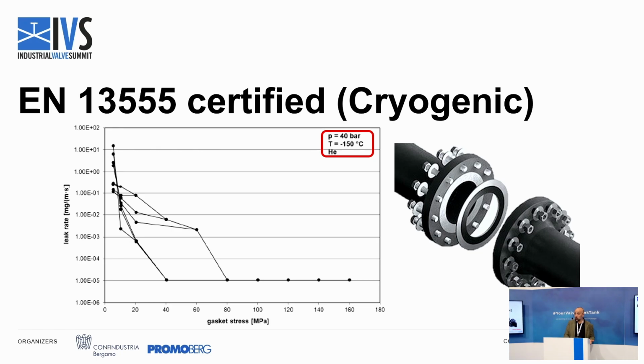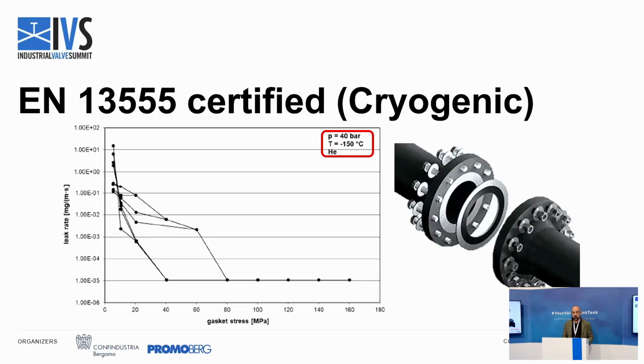Again, we had to change the design of the graphite gasket to face the relaxation and the stress, the compression stress caused by thermal expansion and thermal retraction, and not just the compression of the flange and the gasket between the flange. So we tested it, and again, is another test that is not a standard. So again, we need to be sure that when we ask for something that is qualified, it doesn't mean that it is qualified for the purpose that we need.